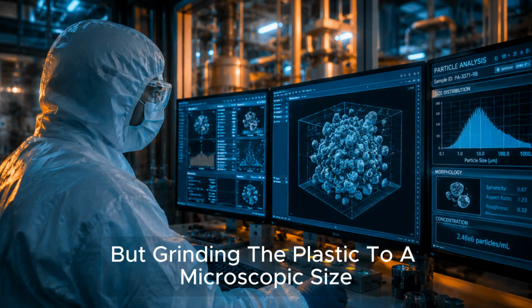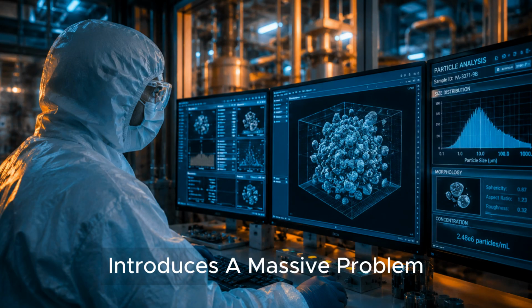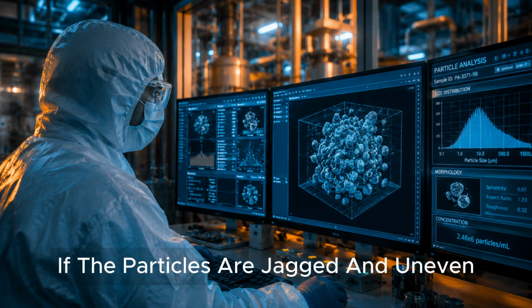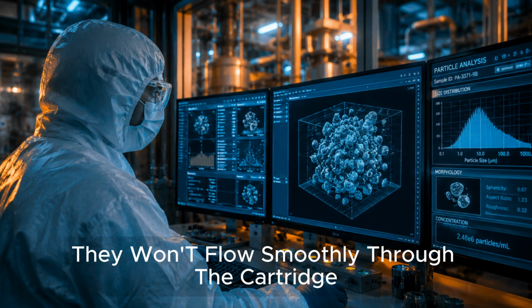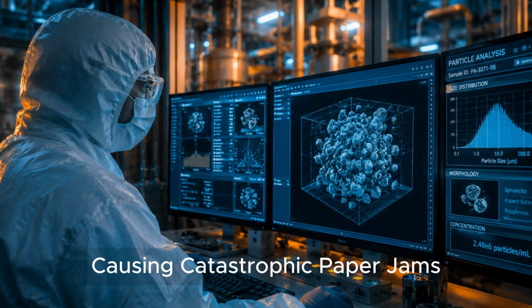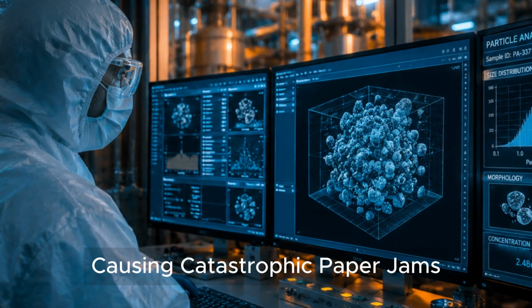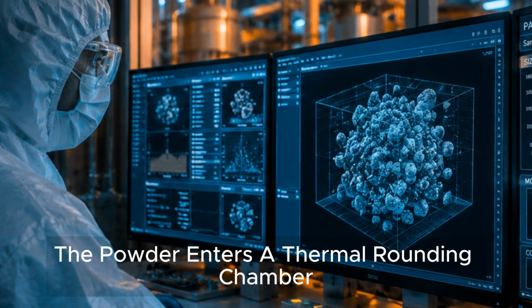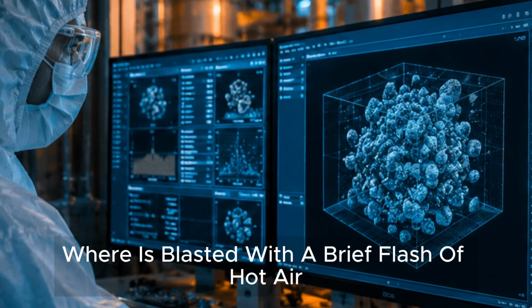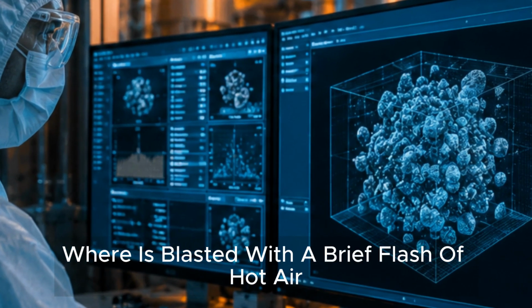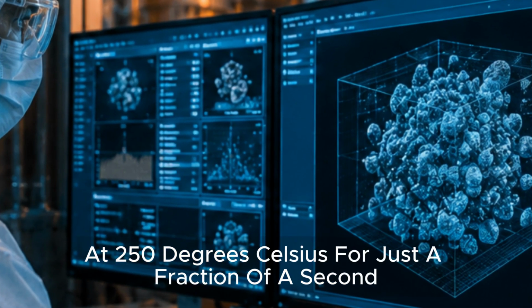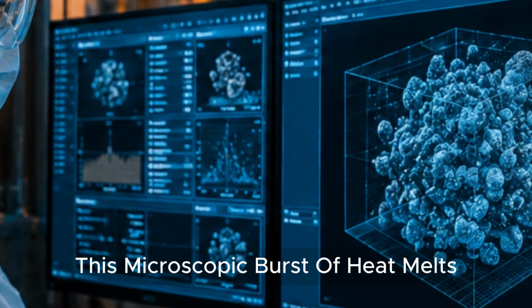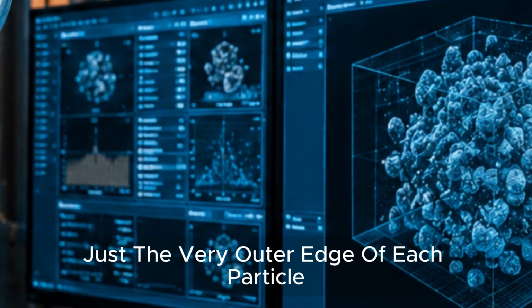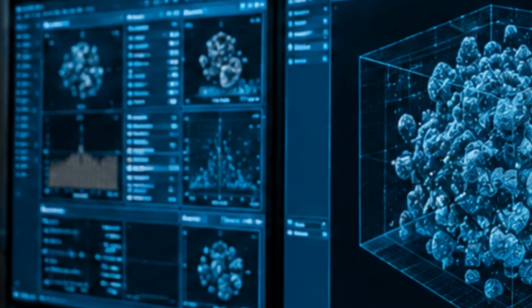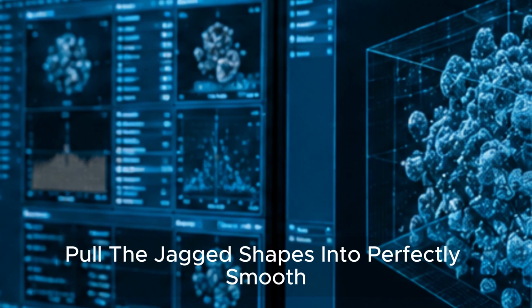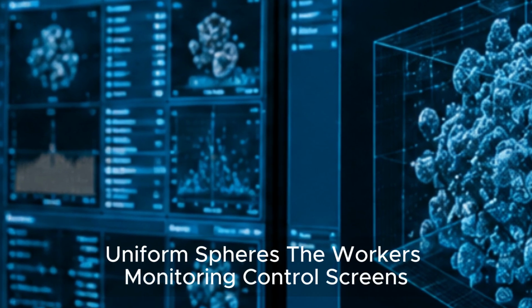But grinding the plastic to a microscopic size introduces a massive problem. If the particles are jagged and uneven, they won't flow smoothly through the cartridge, causing catastrophic paper jams. To fix this, the powder enters a thermal rounding chamber, where it is blasted with a brief flash of hot air at 250 degrees Celsius for just a fraction of a second. This microscopic burst of heat melts just the very outer edge of each particle, letting surface tension pull the jagged shapes into perfectly smooth, uniform spheres.